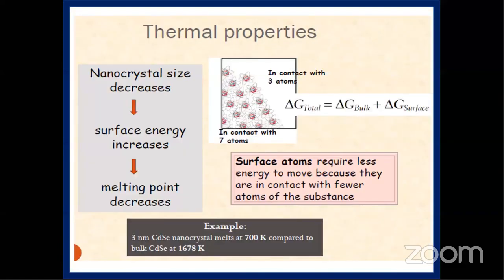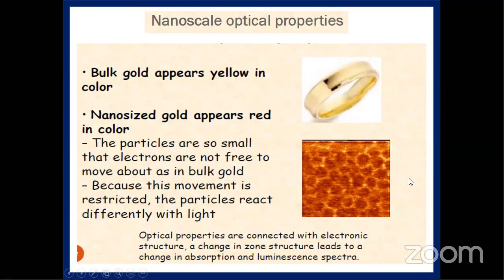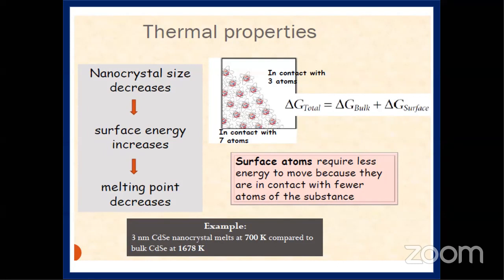You can see this is quite interesting, the thermal property of nanostructure material. When you reduce the size to a smaller scale, the surface energy increases, so the melting point decreases. The reason is the surface atoms require less energy to move because they are in contact with fewer atoms of the substance. I can provide a good example here. You can see cadmium selenide. It is melted at 700 Kelvin as nanostructure material, but for bulk material we need a higher temperature.